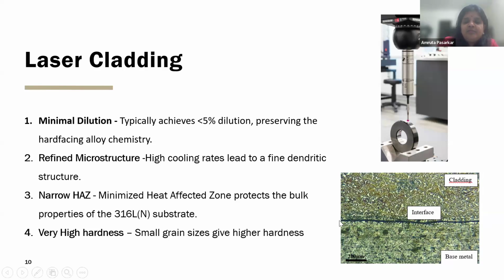So here we can see that we have achieved a very precise line from the laser cladding, and the dilution is also very less. Laser cladding gives a very refined microstructure and a very precise interface. Due to the very fine microstructure and very small grain size, the hardness is also very high in laser cladding.